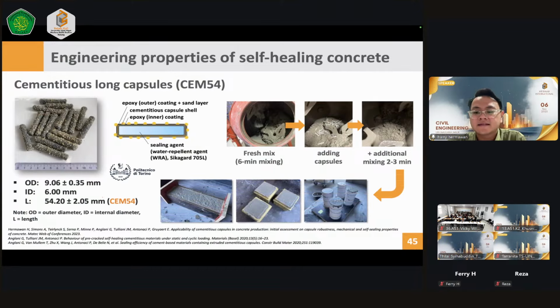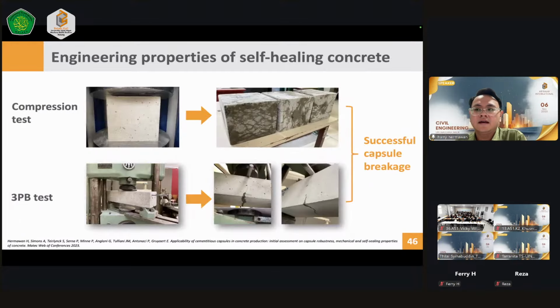Then we can cast this mixture into the molds, either cylindrical molds, cubic molds, or prismatic molds. And then how can we evaluate whether the integration of the capsules, the macrocapsules in particular, is effective or not? We can do the compression test or 3-point bending test. This is an example from my research. When I'm doing the compression test on the capsule-based concrete, you will see what the result is.